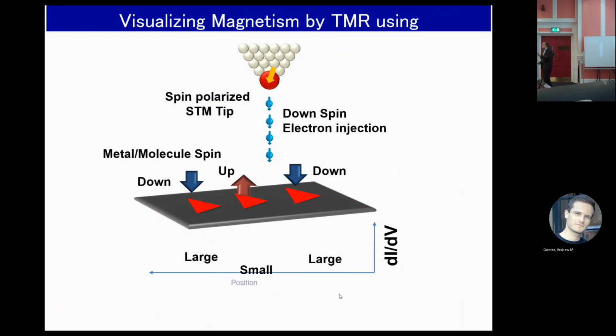So now you must distinguish spin up or spin down, 0 or 1, okay? But then we must visualize the magnet by tunnel magnetic resistance. When the spin of the tip and the spin of the single magnet are down, division is 0. In this case, the spin color is dark. Up spin color is bright. Down spin is dark, up spin is bright. So depending on the direction, the spin color changes. Now the spin color is bright, then spin up. Now the spin color is dark, now spin down.